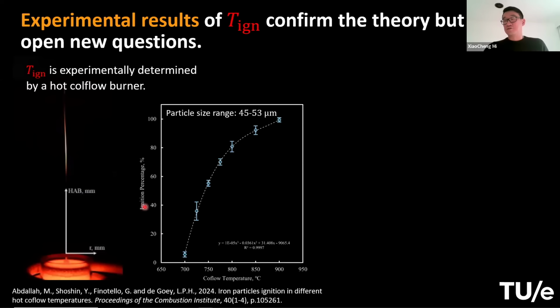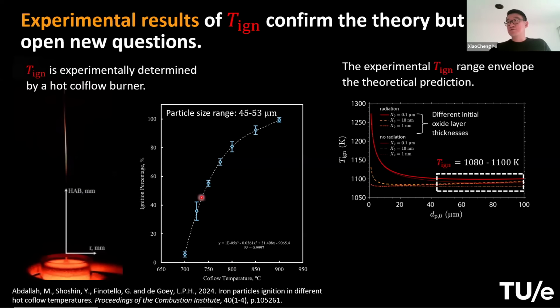And here is the result. What you are measuring is that you count the number of particles you observe, and if one is ignited, you count it as ignition. After measuring many particles, you get this ignition percentage as a function of co-flow temperature. You see this ignition percentage goes from nearly 0 to nearly 100%, from 700 to 900 degrees Celsius over this 200-degree range. This range seems to envelope the theoretical prediction. In this case, I'm comparing it to the case where I assume the particle initially has the same temperature as the gas. This is because the particles are carried with inert gas in this central tube, and before it encounters oxygen, it has already been heated to about the same temperature as the co-flow.